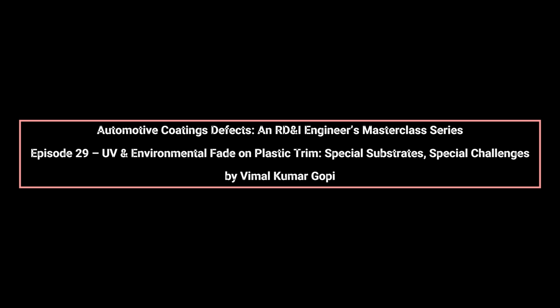Curing and coating formulation are pivotal. Undercured coatings are softer, allowing contaminants to penetrate and increasing early additive depletion. Overcured coatings resist chemical penetration but are brittle, making them prone to microcracking under thermal stress. OEM bake profiles and formulation optimization are validated for specific plastic substrates because mechanical and chemical tolerances differ from metal panels. Even slight deviations in film thickness or solvent balance can have outsized effects on long-term fade resistance.